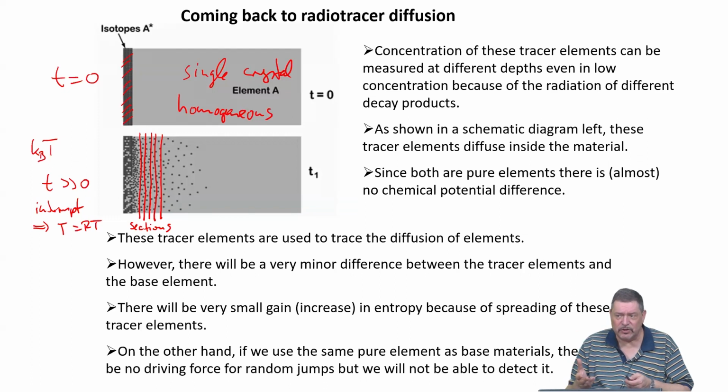And the detectors which you can use for gamma or beta decays are very, very much more sensitive than any method that relies on counting atoms. So the sensitivity contrast is of the order of 10 to the 4 to 10 to the 5.